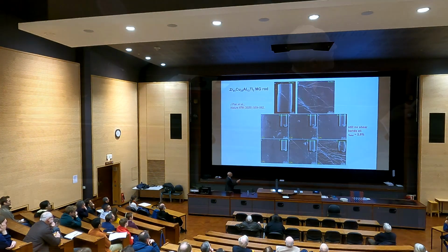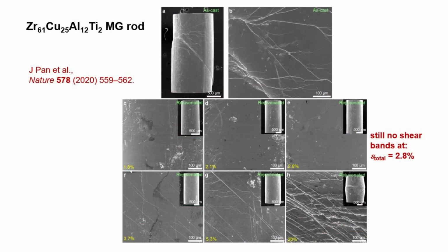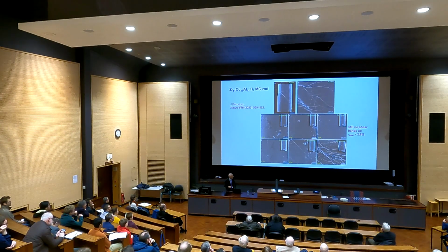So if you have no pretreatment, as soon as you compress this cylinder, it forms shear bands. But if you do the rejuvenated one, you can get to nearly 3% strain with not a hint of shear banding, and it's true plastic deformation. So you really do eliminate shear bands with appropriate treatments.